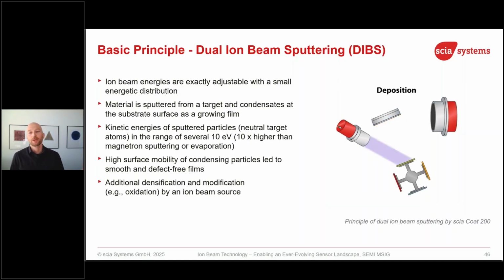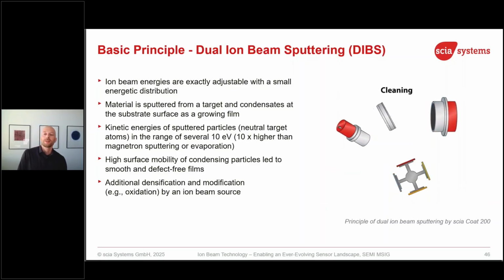And ion beam sputtering means we use an ion beam from an ion beam source, etching material deposited on the sample. Usually you just use a metal target, and if you want to do oxides or nitrides, we add oxygen or nitrogen into the process. There is an additional cleaning ion beam source, which could be used for pre-cleaning of the substrate itself.